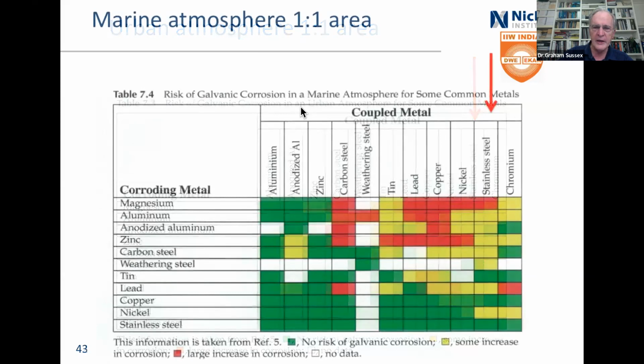If you're looking in a marine atmosphere, so there's lots of chlorides around, and again, magnesium, yes, weathering steel, not so hot, but that's partly because weathering steel doesn't like chlorides. Tin, yeah, that's now back being okay because the corrosion's gone up. Lead, bit doubtful. Nickel, a little doubtful, which is an interesting statement. But this is useful for a first past the post. And then you look at your area ratios, and then you look at the actual environment. How bad is the marine atmosphere? But this is in atmospheres, it's not submerged.